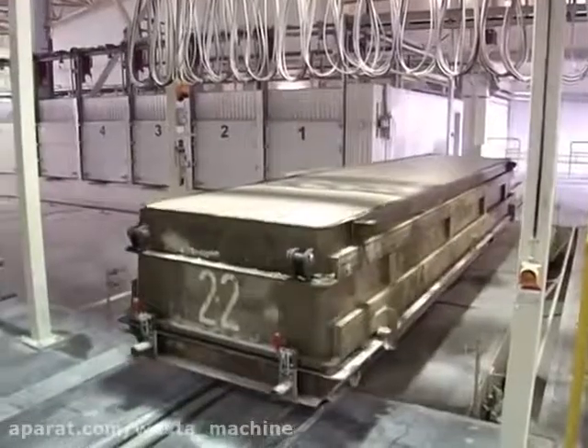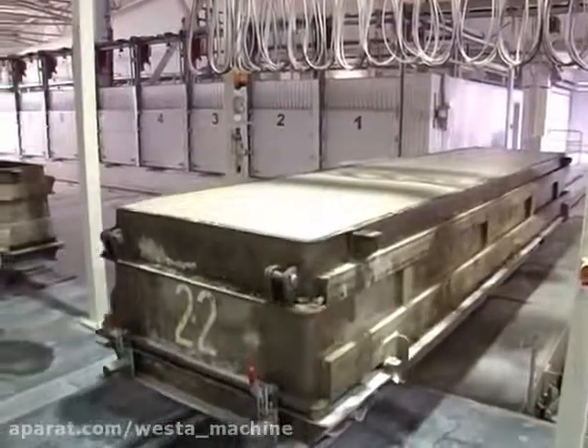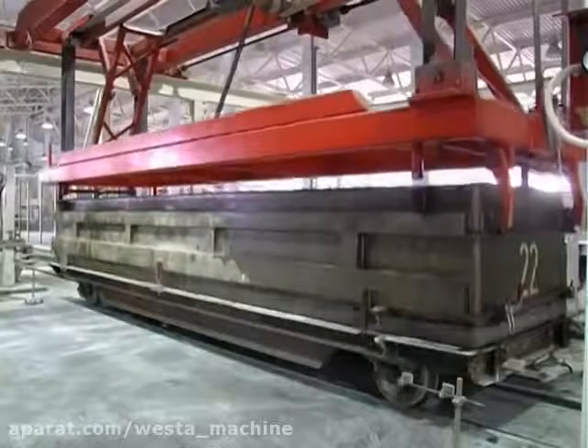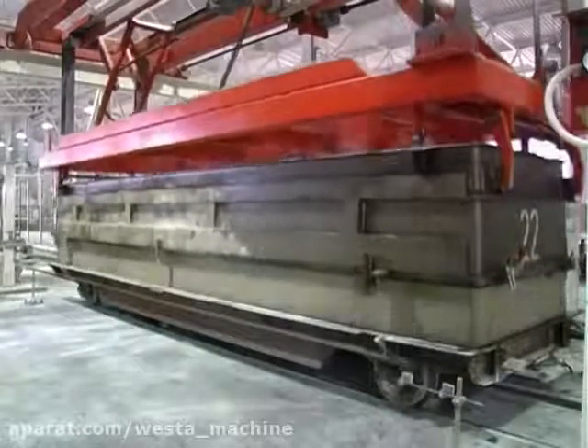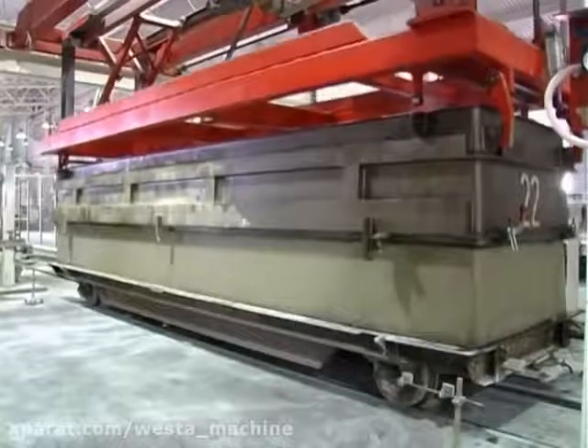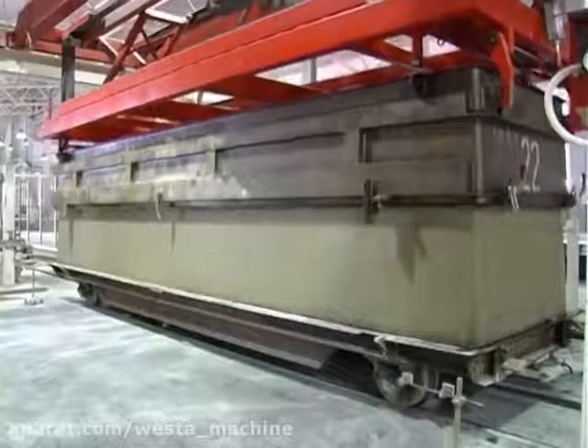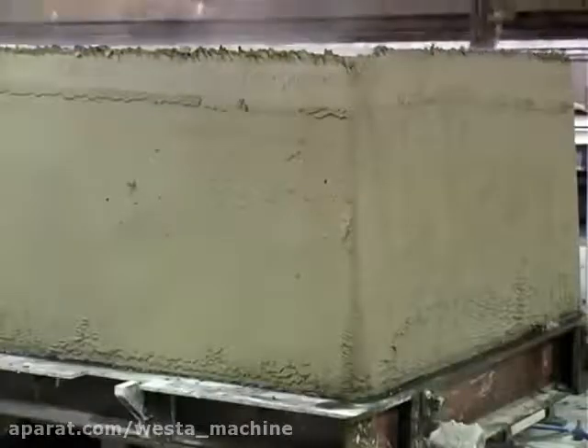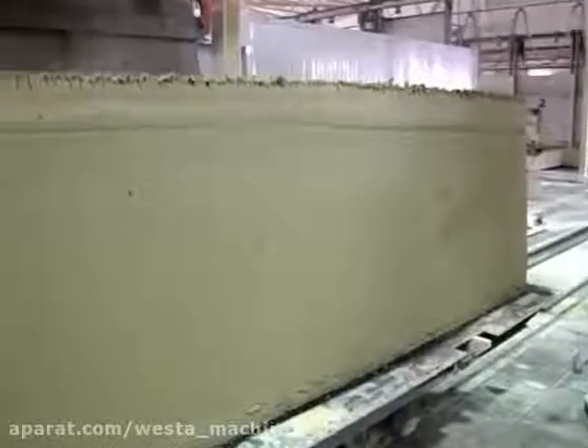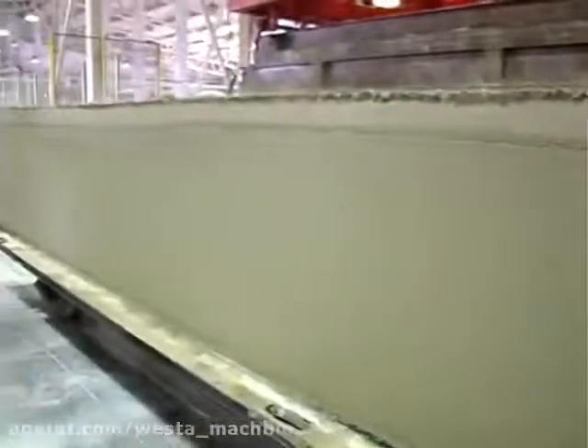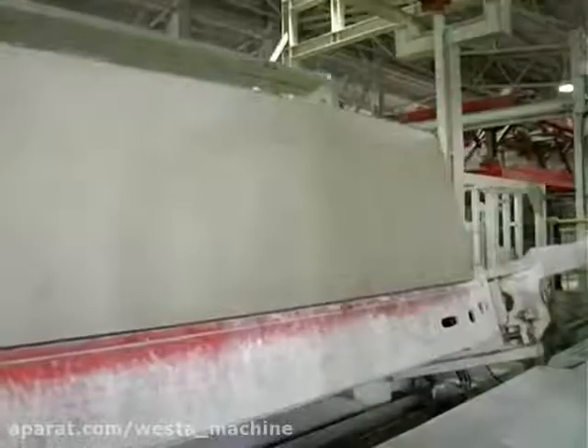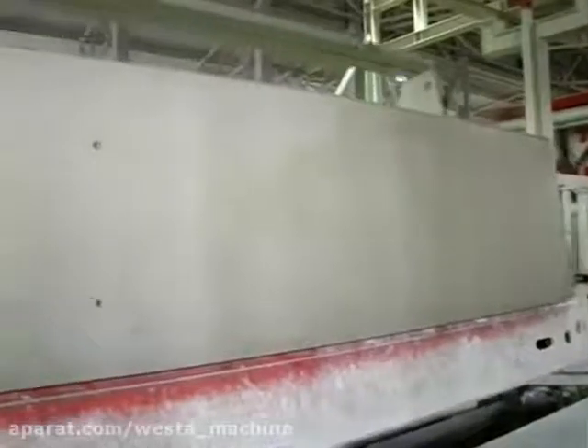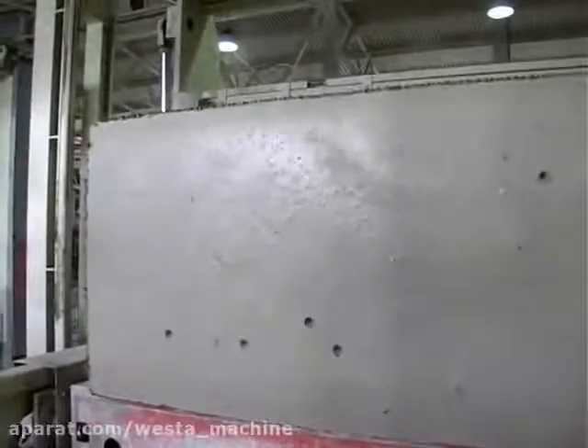Westa casting molds are specially designed for gentle and high-quality separation of a cake from the mold. There is a portal device used for mold detachment from the base. The cake is moved very carefully to minimize possible damages, which can only be seen after the autoclave treatment of AAC blocks. Now, the cake is quite soft, that is why it can be calibrated and cut into blocks of preferred shapes and sizes without much effort.